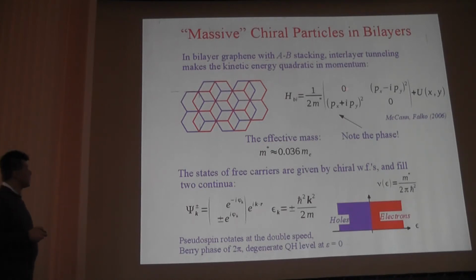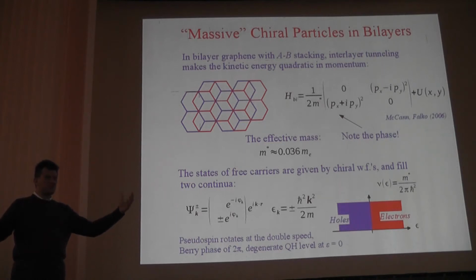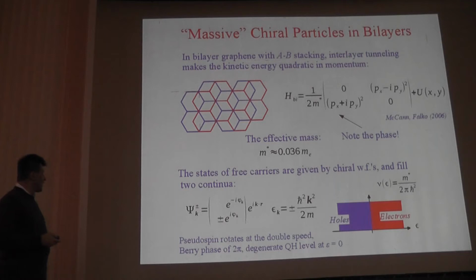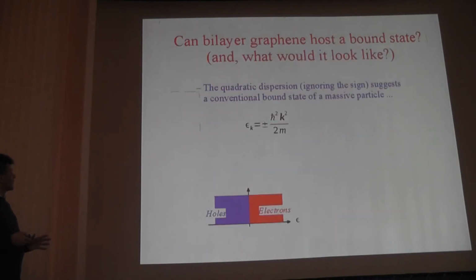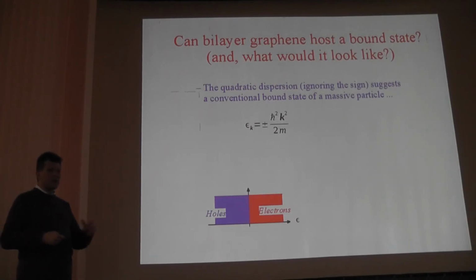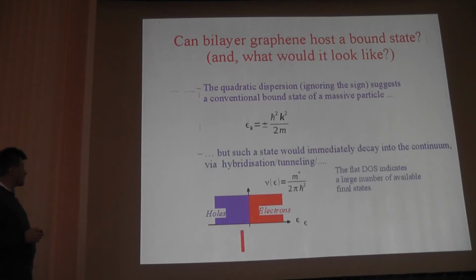I'd like to mention one project involving bilayer graphene. So one can ask what happens if you place a very strong impurity in bilayer graphene? Will it create a resonance like this? Well, first you can start working on this by thinking what are the naive expectations. So here I have electron continuum, here I have hole continuum. If we try to put an impurity in graphene so that it would drag an electron state into the hole continuum, I will face the following problem. The density of states in the hole continuum is very high, so if there is any coupling between the states and the continuum, the state would dissolve into the continuum almost instantly. The only way out of this is if the coupling is somehow suppressed.